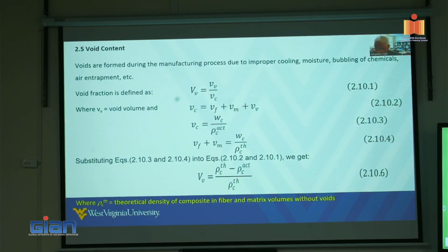But the important message here is that, as a thumb rule, if you have 1% of voids, that will reduce the strength of the composite by about 7 to 8%. So that's why you need to minimize the void. In practicality, the void percent should be around 1% or even less. Many factors play a role in void formation, including temperature and cure rate. But now I will not go into too many details in that regard.